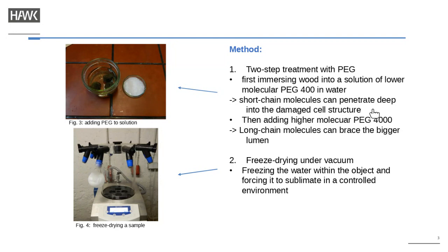Later on, you can add a higher molecular PEG. In this case, it was 4,000. And the long chain molecules can brace the bigger lumen. They're not filling them completely, but holding up the structure from within. The freeze drying process under vacuum can very, very basically be broken down into freezing the water within the object and forcing it to sublimate in a controlled environment while leaving the PEG behind.